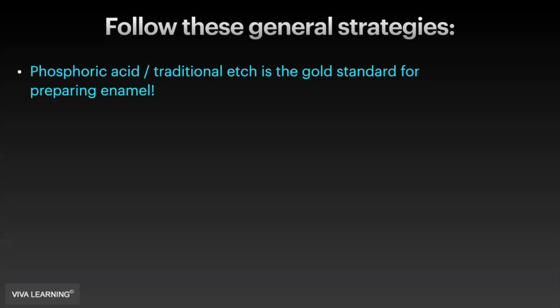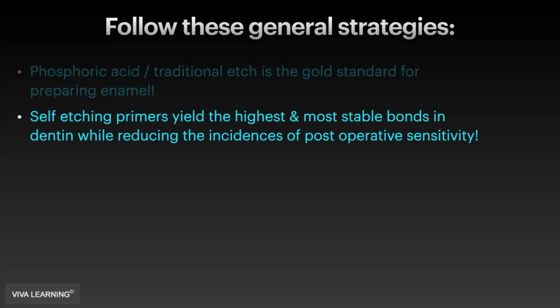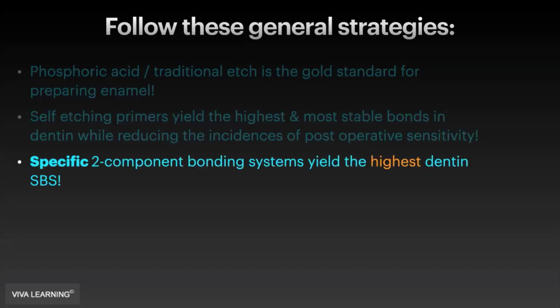That doesn't mean we can't bond to enamel with self-etching primers. It just means we're not going to get as predictable or lasting a bond because we just can't get the same etch patterns. So when you have enamel, we want to be able to use phosphoric acid. That being said, I grew up in the era of total etch, where we would etch enamel and dentin. And right now, the self-etching primers seem to yield, at least what our independent studies show, the highest and most stable bonds in dentin. And at the same time, they tend to reduce the incidence of postoperative sensitivity.